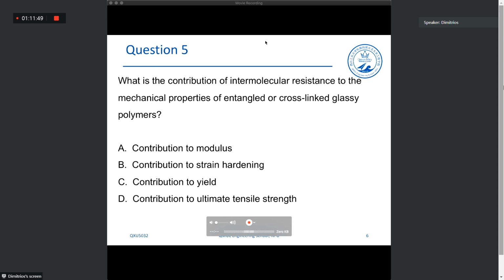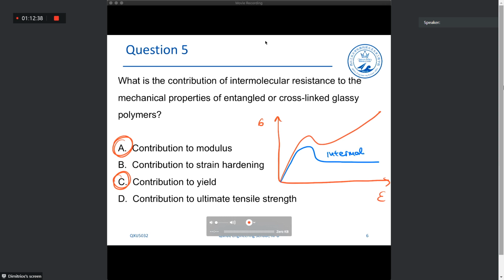So for the polymers group, the results were quite shared between answers. Let me check the materials group. I'll give you the answer. Same here. So in this case, the correct answer is contribution to modulus and contribution to yield. We said for an amorphous, glassy polymer that can form a neck, the stress strain curve looks like that. If we decompose this curve into two elements, we have the contribution of the intermolecular resistance. Okay, this is the intermolecular. And also we have the contribution of the network element component.